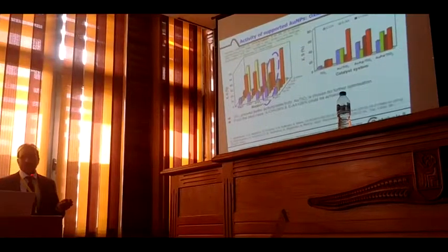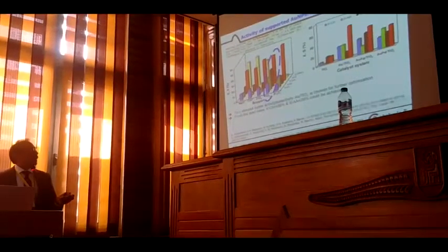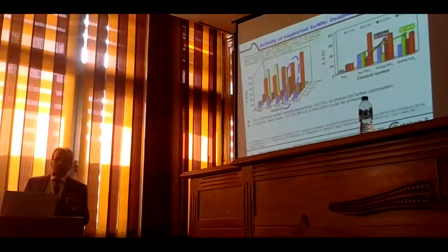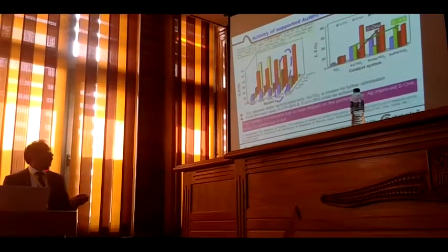So after this monometal catalyst, we thought, okay, how to improve adipic acid selectivity at acceptably high conversion. So we tried to dope a second metal, and we used silver and palladium in the same concentration as gold, 1% each. When we add silver, the selectivity of cyclohexanone is increasing, the black one. But when we add palladium, adipic acid is increasing, but not to the extent we want. But there is some improvement. What we learned from this study is that the second metallic component has some influence, and both are behaving differently. Silver improved the selectivity of cyclohexanone, and palladium enhanced the selectivity of adipic acid.